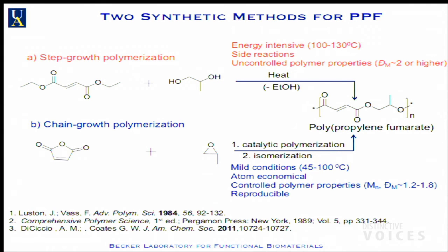Okay, so this is molecular mass distribution, which is basically a distribution of chain length. And when you have very tight control over chain length, you can control degradation, which is what we're really after in this process. And more importantly, it's reproducible. Same conditions work at 5 grams, work at 50, work at 5 kilograms, work at 500 kilograms.